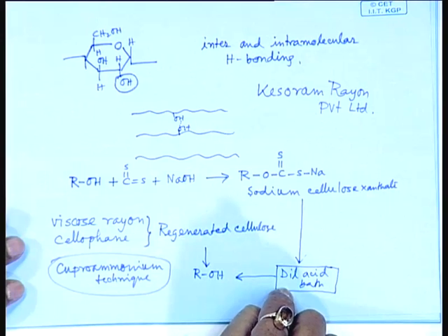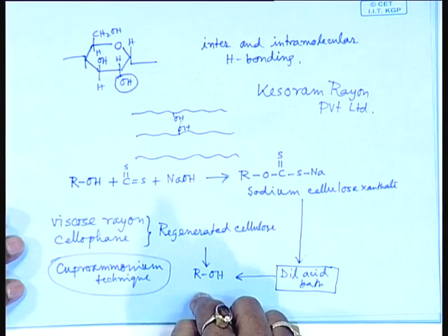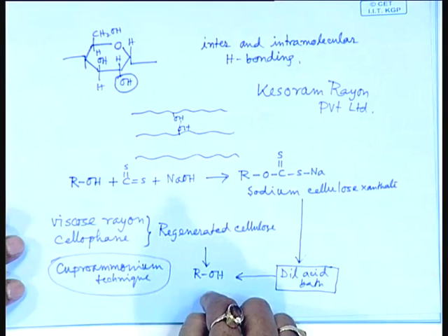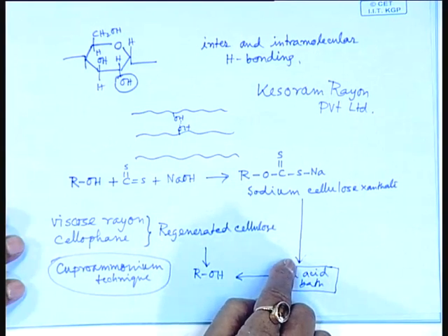You can verify it. You take the XRD of raw cotton, then you take the X-ray diffraction of this mercerized cotton, you will find that its crystallinity is reduced. That is due to decrease in hydrogen bond. Also, you can verify this with the help of Fourier transform infrared spectroscopy. There you will find that the extent or concentration of hydrogen bonding has been decreased after this viscose treatment.